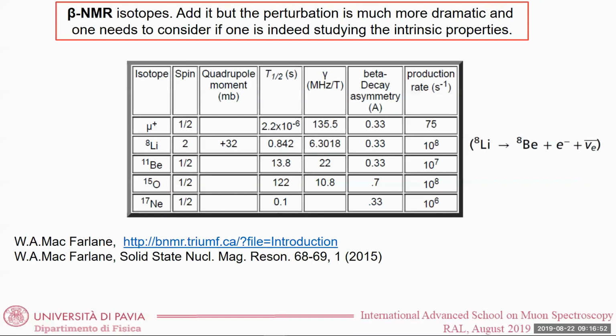However, when I put all these nuclei in, I'm not making a small perturbation to my system. I can even create defects. Of course, this can be relevant, for example, if I want to study pinning centers in superconductors and I want to produce defects, and I can use the probe which produces these defects to study their effect on the pinning of the flux lines in superconductors. Another case where it can be relevant is to study ionic diffusion in certain systems. If I want to study lithium ionic diffusion, I can put the lithium inside, and then I can study with beta NMR the diffusion of lithium. But still, in general, it's not a small perturbation. If you want to learn something more, there is this nice review by Andrew McFarlane on beta NMR.